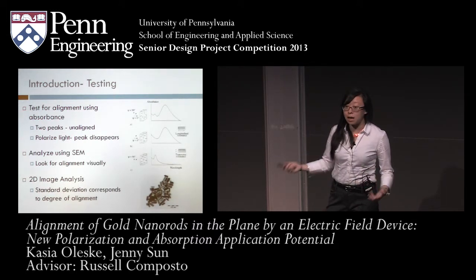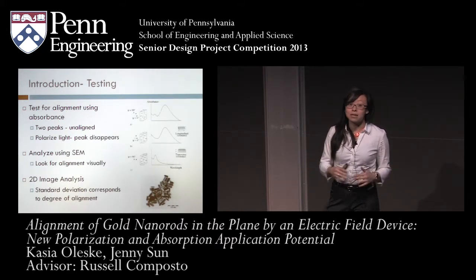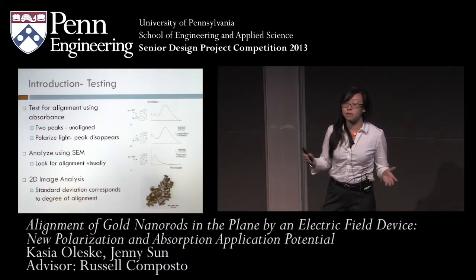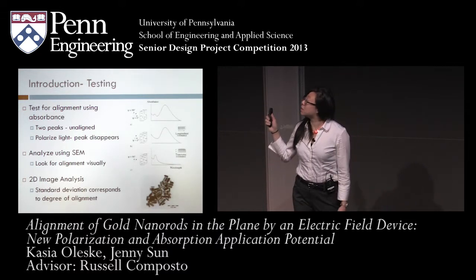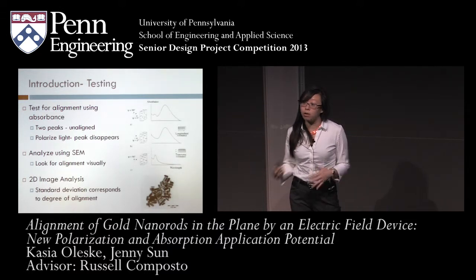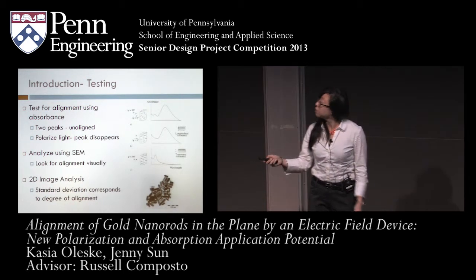Another way we could actually see alignment would be to use SEM. By taking images of the nanorods, we could visually inspect them and see how the orientation was. And then finally, we could take these images, and there's special software that allows us to find the average angle of all of the nanorods in an image, finds the standard deviation within those angles, and then the larger the standard deviation, the smaller the alignment, and vice versa.